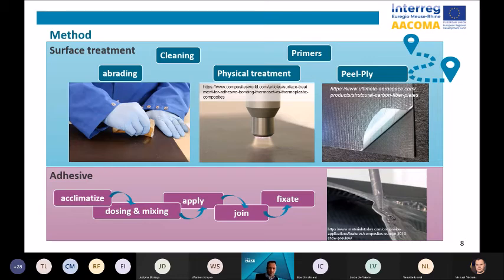But whatever the treatment will be, the first step is cleaning, and the chosen cleaning solvent needs to be able to remove all contaminations but not damage your material. Release agents are often present at composites, and they can be very difficult to remove. And even silicone products are still used as release agents, and it's visually impossible to remove or cover all silicones. You really have to state that these materials are forbidden in your production or at your supplier.